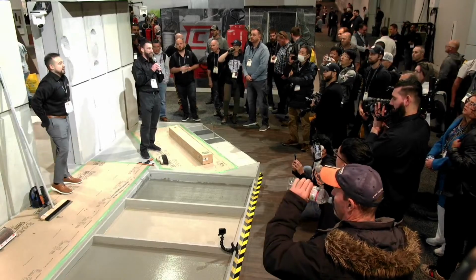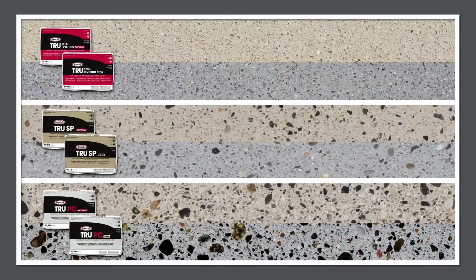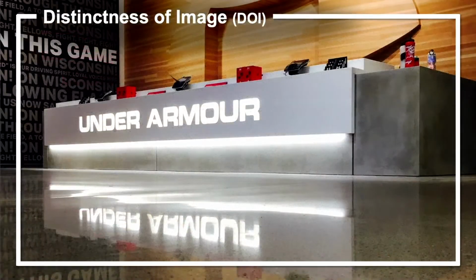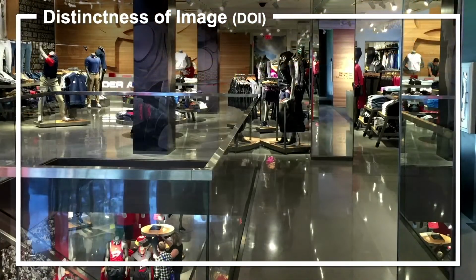Now, all of these products come in both natural and gray colors. They can be colored on the job site or embedded with aggregate to get a different terrazzo look at a much lower cost and with less labor. Now, really what sets the TRU products apart is that they have a very high surface hardness, so they're great to get a very good distinctness of image, or DOI, which is really the ability of the floor to reflect light like a mirror. And as you can see, this Under Armour floor has an excellent DOI, and that's again due to the surface hardness of the TRU products.